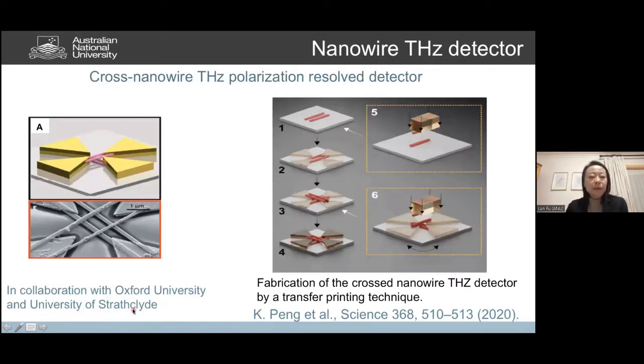And also again, by collaborating with Oxford University as well as University of Strathclyde, we demonstrated a polarization resolvable detector by creating this cross nanowire network. As you can see, we create two nanowire channels, one on top of each other. However, they're not touching, so that we don't have the cross talk and shorting problem. And this has to be done using the transfer printing technique developed at the University of Strathclyde.